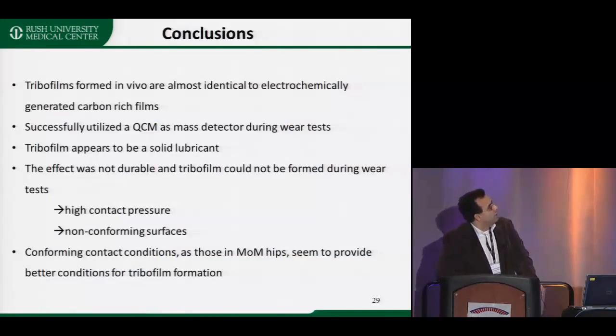What are our conclusions? First of all, the tribofilm formed in vivo is almost identical to the electrochemically generated film. We also successfully utilized the QCM as a mass detector during wear tests. The tribofilm appears to be a solid lubricant. And concerning our setup, the effect of the tribofilm was not durable and it could not be formed during the wear test. There are two reasons.